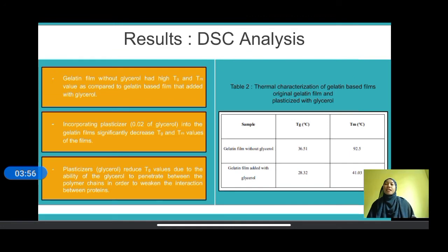And then next, this is the result for the DSC analysis, in which we can see in table 2 that the gelatin film without glycerol had a higher glass transition temperature and melting temperature as compared to the gelatin film added with glycerol. So we can say that incorporating plasticizer into the gelatin film significantly decreased the Tg and Tm values of the films. Plasticizers reduce Tg values due to the ability of the glycerol to penetrate between the polymer chains in order to weaken the interaction between the proteins.